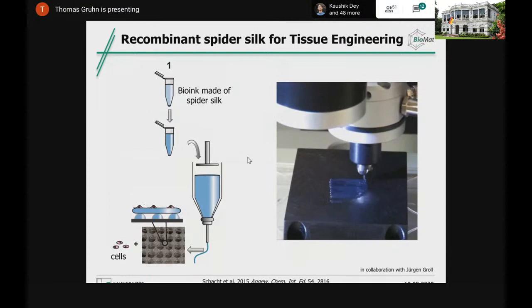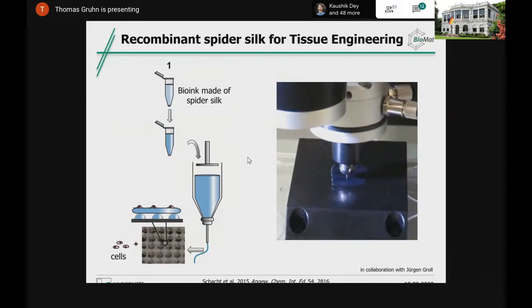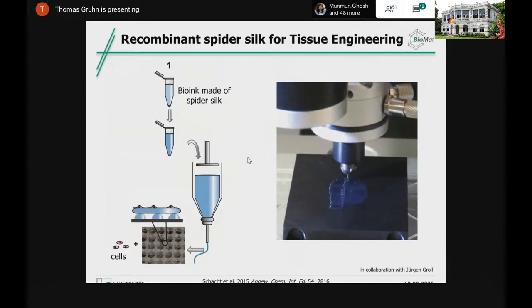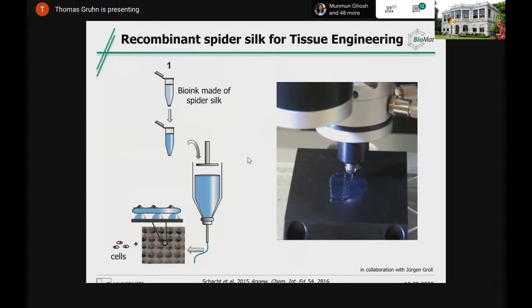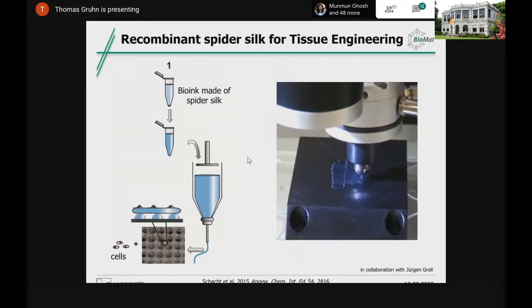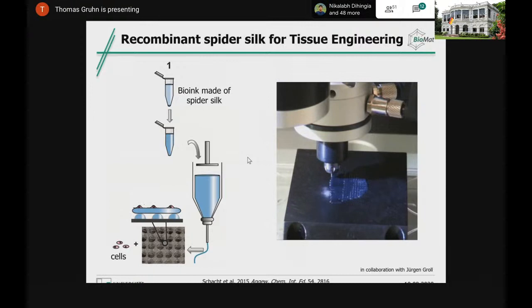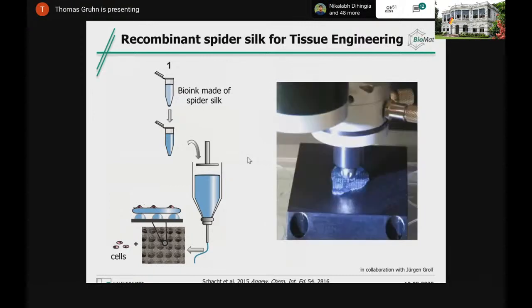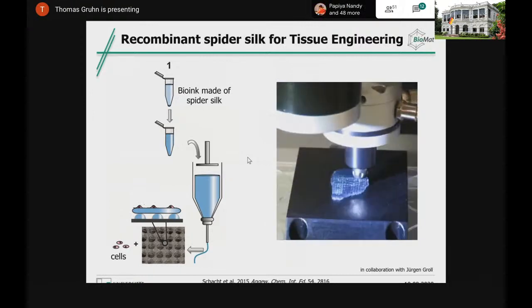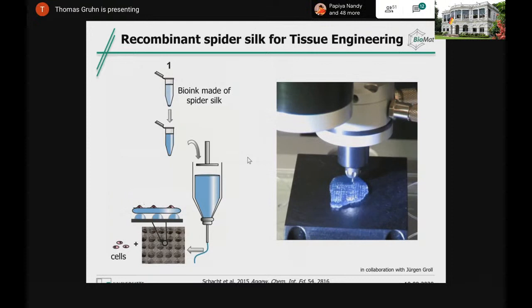If you just open the tube, nothing happens. You have to squeeze it, then it flows. As soon as you remove the shear stress, it hardens immediately. Without additive, there's no chemical crosslinker in there, there's nothing in there. And here you see what we printed was an ear-like structure, and we really can actually print it in any kind of dimension, and we can implement cells, and this is called biofabrication.